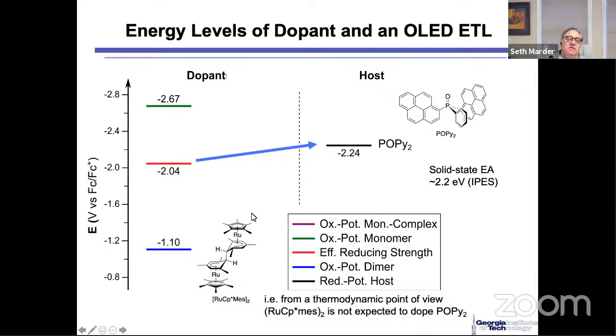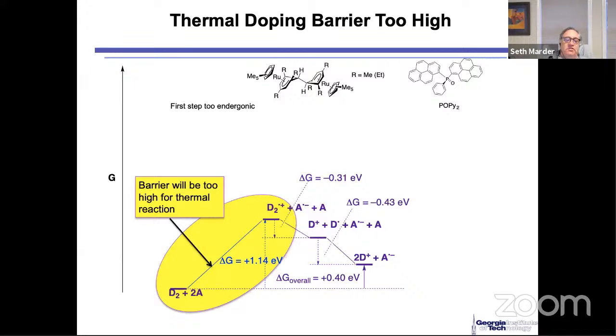In other words, if we took this plus 2 of these, we're going uphill by 0.4 of a volt. Okay, so it should not happen. It should be uphill. Okay, so that's shown here. What's shown here is a potential energy diagram that says, look, this first transfer of an electron from here to there, it's uphill by 1.14 volts. And then if we do the cleavage, which I've told you about, and then we do the electron transfer, we're still uphill. Thermodynamically, we're uphill.